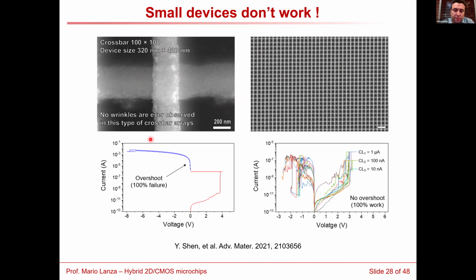And we observed something interesting. We also apply a current limitation. In this case, we apply 1 microamp because these devices are small. We apply the positive ramp, and then we observe the dielectric breakdown. However, during the reverse ramp, we observe that the current increases orders of magnitude above the current limitation. This did not happen before.